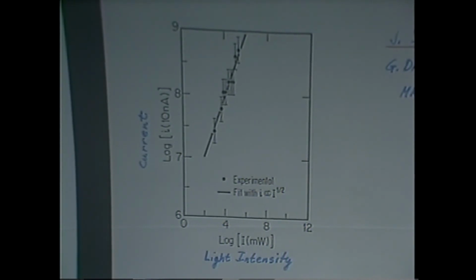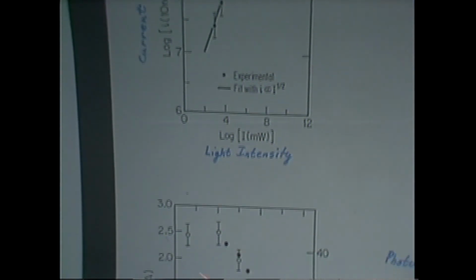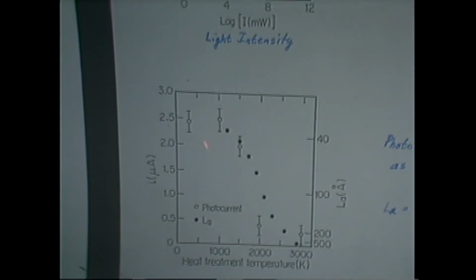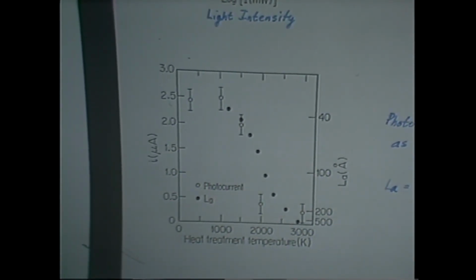photoconductivity. Now, the good part about it is that you can use this method to characterize, since the photoconductivity is in disordered fibers much more than it is in ordered fibers, it's a way of measuring disorder. And we're trying to understand how we can correlate this with mechanical properties and do something in the engineering area.